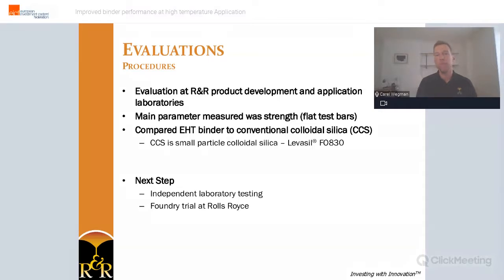We went through three different trial stages. The first evaluation was done in-house at the R&R lab in Miami, USA. Based on the Rolls-Royce criteria, the main parameter measured was MOR strength. For the internal trial, the material was compared to a conventional small particle colloidal silica, which we will call CCS through this presentation. At a later stage, the project proceeded further with testing at an independent laboratory and a foundry trial at a Rolls-Royce plant in Derby, the UK.